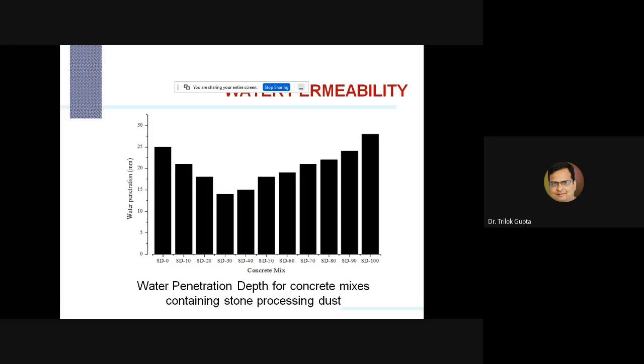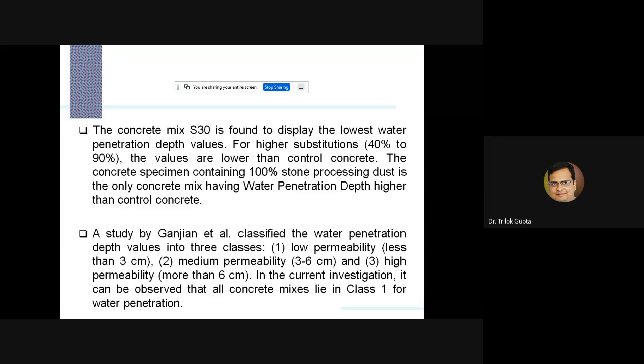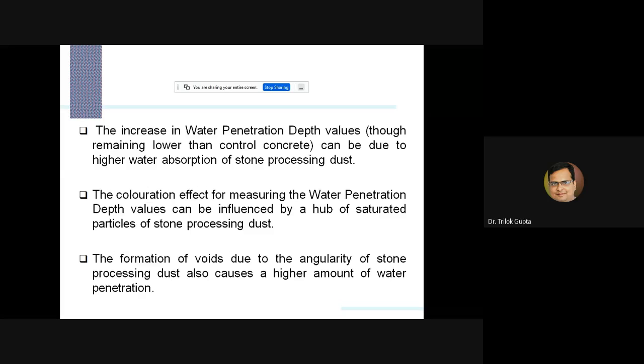According to one researcher, Ganjian et al., water penetration depth is classified into three classes. If the water penetration depth is less than 30 mm, it is in the category of low permeability. If it is between 30 to 60 mm, it is classified as medium permeability. If it is more than 60 mm, it is high permeability. And in our case, in all the cases, it was less than 30 mm. So we can say our concrete had low permeability.